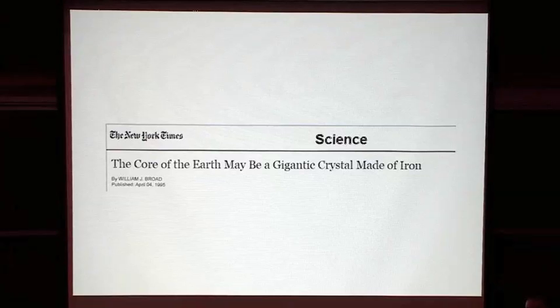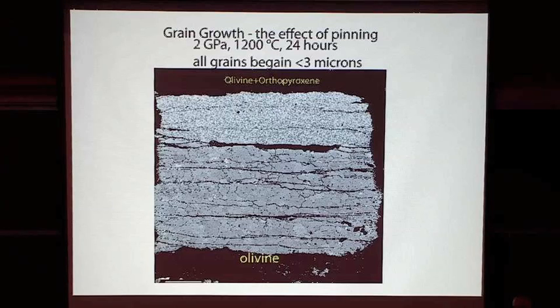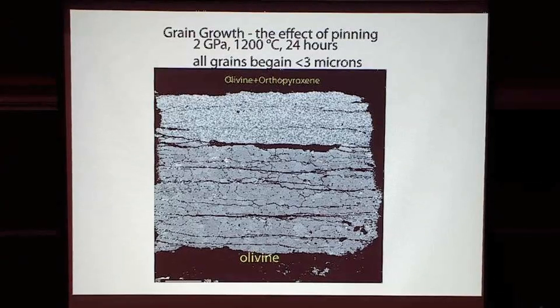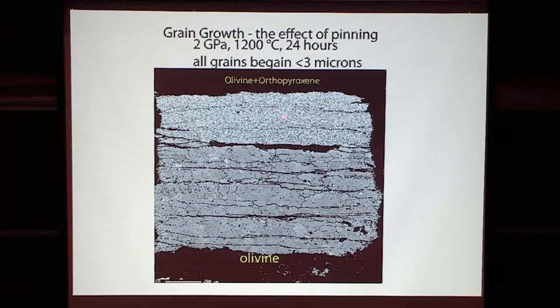Two reasons. One is that grain growth really isn't as simple as you might think it is when you talk about a rock as compared to, say, an aggregate of a pure phase like olivine. So this is yet another unpublished experiment. What we did is we put in micron-sized, I think 3 micron-sized, olivine powder into a high-pressure apparatus, and then over that we put olivine and orthopyroxene of the same grain size. So this all started out as 3 micron grains. Held it there for 24 hours, 1200 degrees, which isn't that hot. And at the end of the experiment, the olivine and the orthopyroxene remained about 10 microns, and the olivines, I don't know the exact size, but there's a 200 micron scale bar.